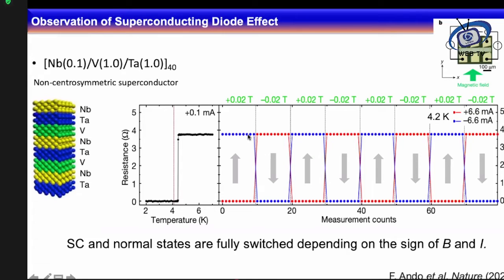And another very interesting thing that they observed is the effect of the applied magnetic field. For example, we keep our resistance at a zero resistance value with the positive current, and we don't change the polarity of the current, we only change the direction of the applied magnetic field, which was in plane but perpendicular to the flow of current. Now here, in the zero resistance state, our magnetic field is positive, for example, upward. And then if we switch it to downwards, the device switched to the normal state.